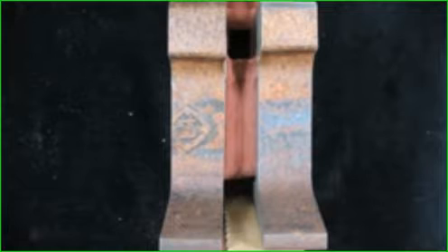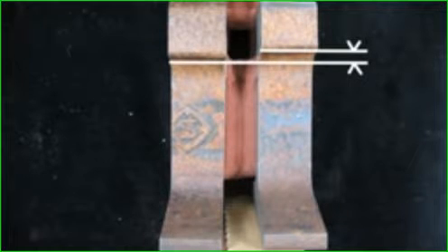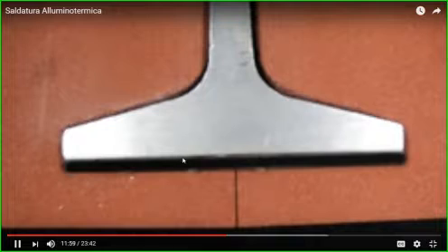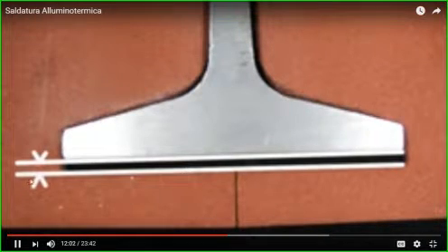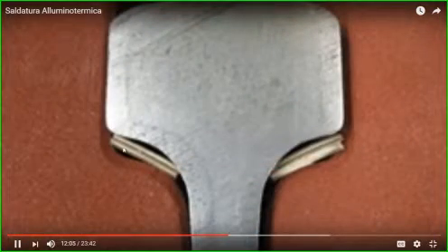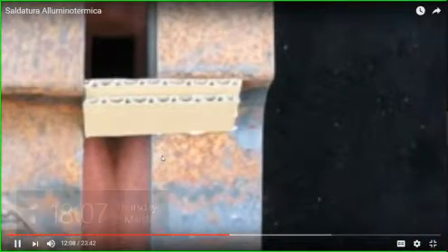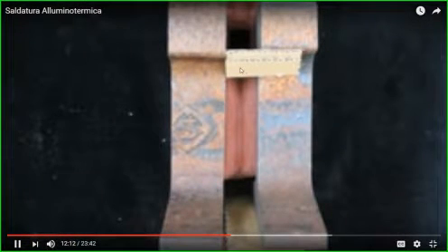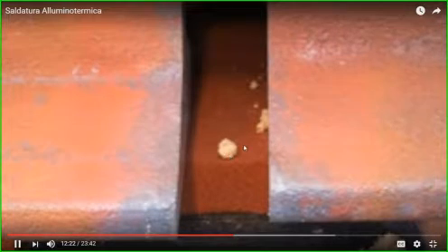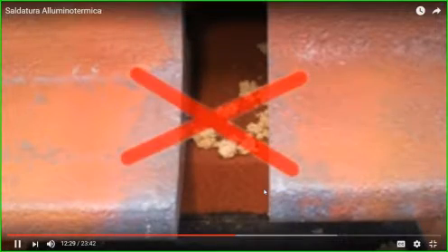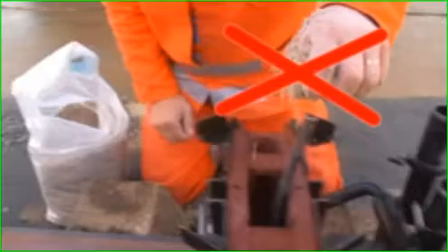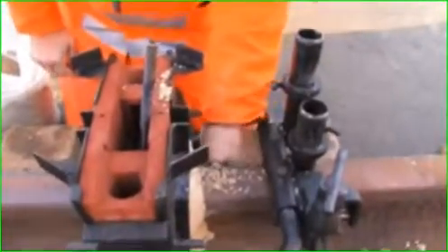If differently worn rails are to be welded, then spaces will unavoidably occur between the mould and the rail under the foot and head of the more worn rail. These spaces must be filled with cardboards, while the cardboard's corking mustn't project beyond the mould surface. As you already know the principle from luting at the railhead, here the luting sand is also to be pushed against it, and this way create the compact sand barrier for the liquid steel. By lack of these cardboards, the sand would be pushed through the space inside the moulds, and would result in sand inclusions in the weld. Luting is to foreclose any falling of sand into the moulds, as sand inclusions in the weld would be the result.